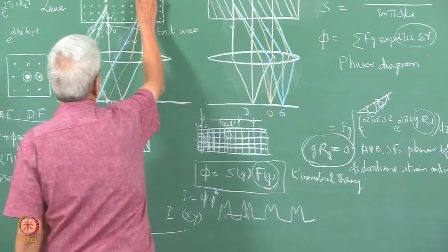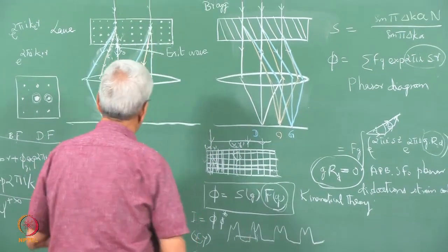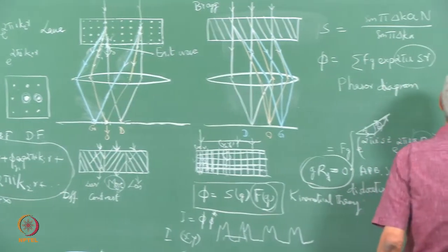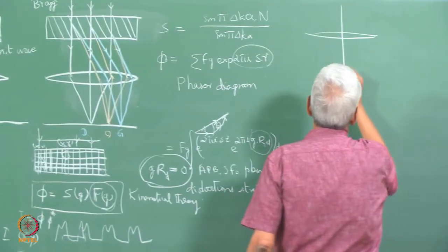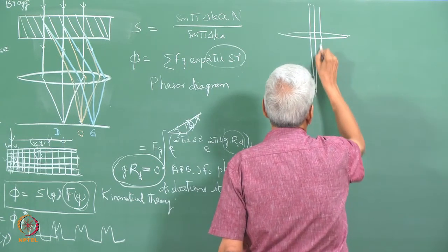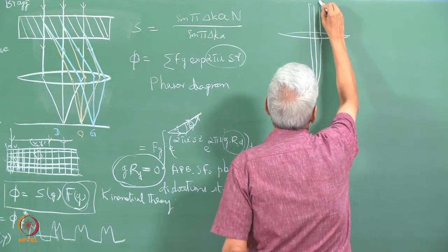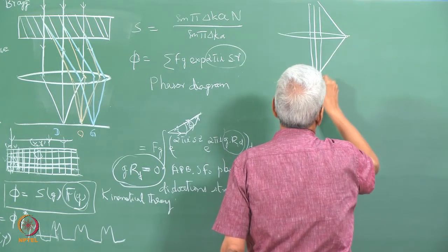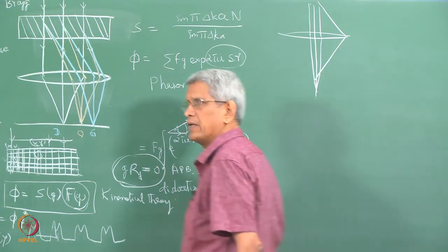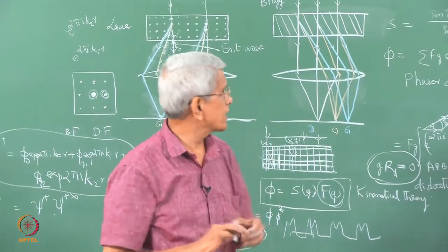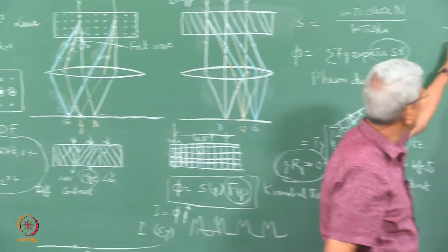Since we consider the electron beam as a wave which is passing through that sample, what does that lens do? As we have studied earlier, the rays which are travelling close to the optic axis are focused at some particular point, and the rays which are travelling far away from the optic axis are focused elsewhere. So, essentially this should also have been brought to this point. That is not happening because some path difference or phase has been introduced to the beams which are scattered in different directions by the lens itself. So, some additional factor.